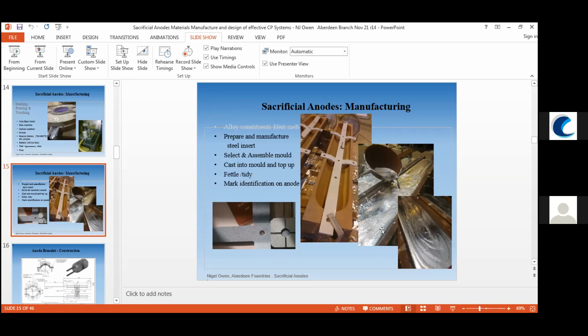And you can actually put some of these materials through die casting, etc. But it's very tricky because of the large shrinkage, and because of the composite nature of it, the differential expansion of the steel bars and the materials there. And you do get some movement and bending, etc., if you don't control it. So tricky product, and not a standard sort of foundry thing. You're not making engine blocks here.